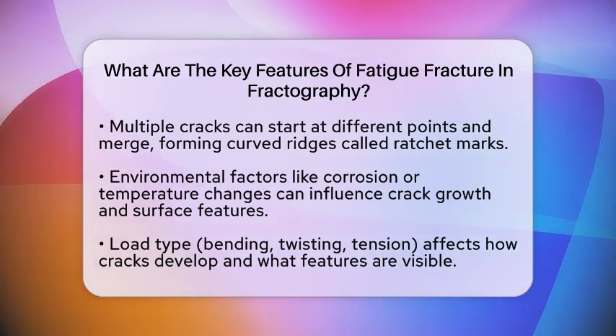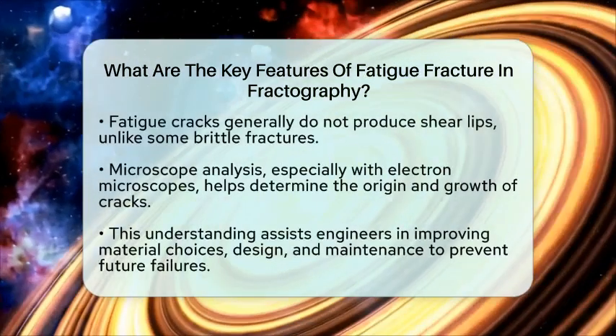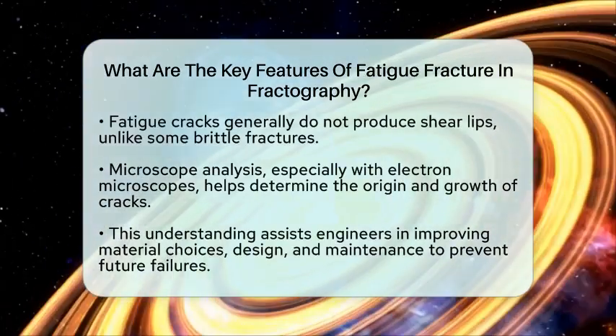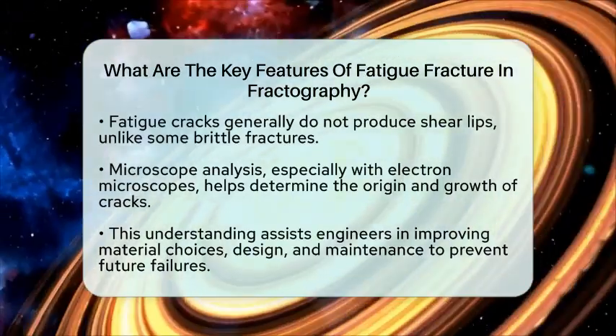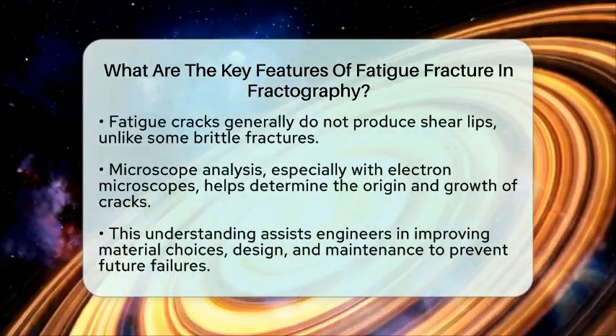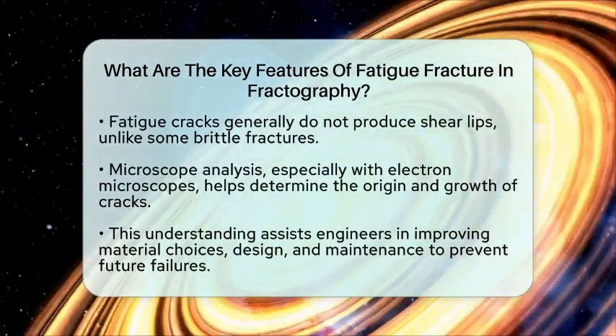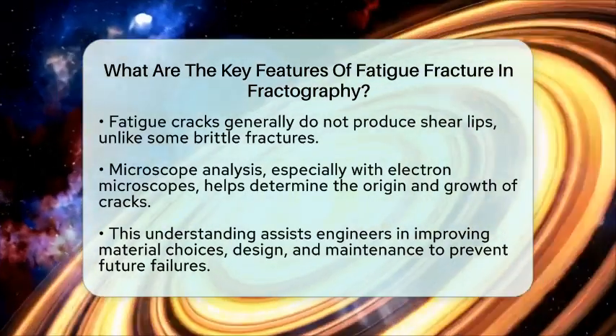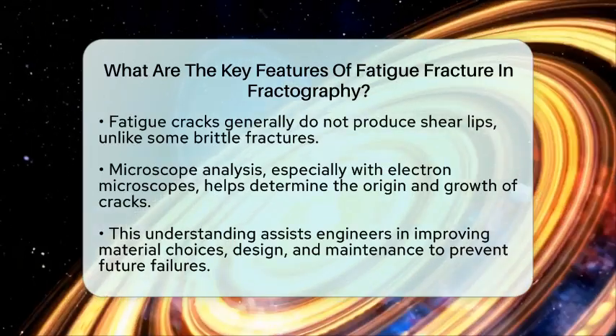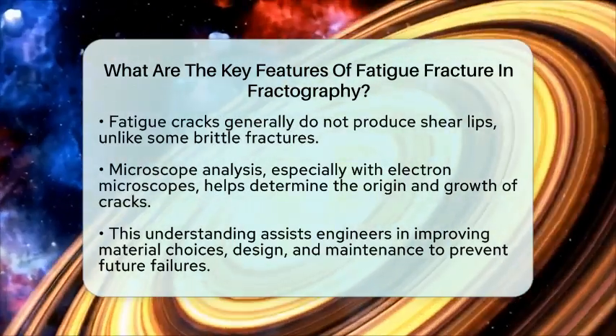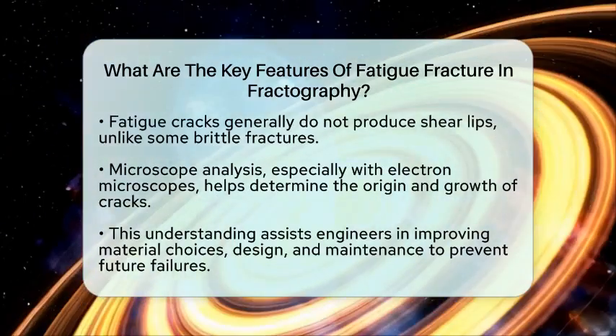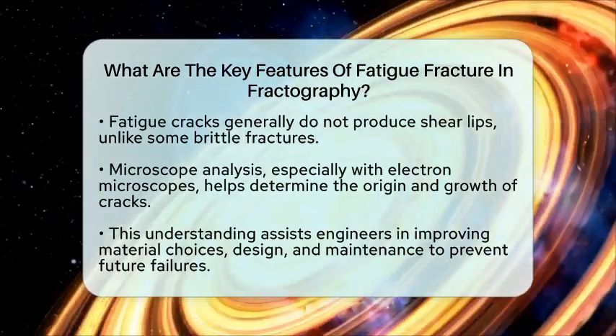Unlike some brittle fractures, fatigue cracks don't usually produce shear lips, which are angled edges seen in other failure types. Looking at these features under a microscope, especially with scanning electron microscopy, helps failure analysts piece together the failure story. They can identify if a crack started at a defect or was caused by repetitive stress.